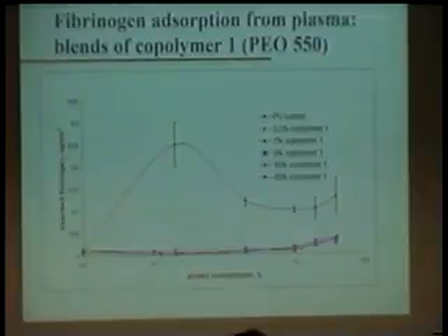This is what you typically see for fibrinogen adsorption in a plasma system, and it reflects the fact that the fibrinogen, which is an abundant protein in plasma, tends to be adsorbed in abundance initially. And later on, it's kicked off the surface by other proteins which are present at lower concentration in the plasma, but have a higher affinity for the surface. This is actually not a time axis, but it transposes that way. Anyway, as you see, there's no Vroman effect whatsoever on those blended materials. And so even at very low plasma concentrations and small times, there's just nothing on there. The surface doesn't want to adsorb fibrinogen.